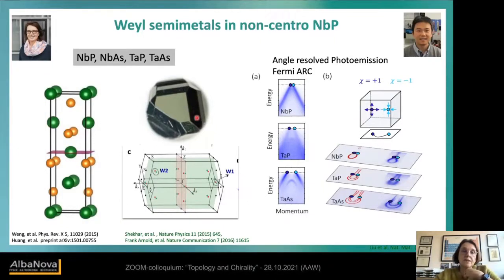But then we were also able to grow single crystals, a whole series of compounds. And you see here the angle-resolved soft photoemission. So you see really that you have bands which are nearly crossing at the Fermi energy. And if you increase spin orbit coupling, which means you make the material heavier, so niobium is lighter than tantalum, you see that you have a spin orbit splitting here. So the bands are more split, but also the distance between the Weyl points becomes larger.